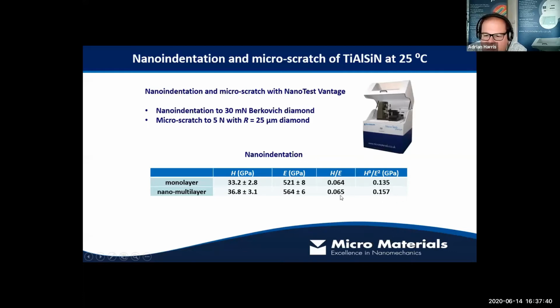So the hardness to modulus ratio is one indicator, and the hardness cube to modulus squared ratio can give us a useful measure of how able the material is to deform plastically as opposed to fracture brittle. And so the suggestion would be that this nano multi-layer is likely to outperform the monolayer.